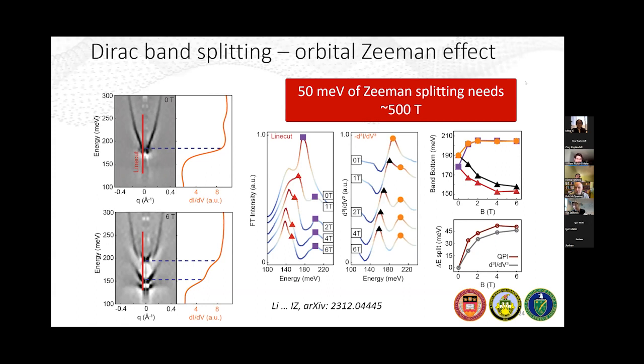What's really prominent in this system is this Dirac dispersion. Now we've imaged it in two different materials, and it seems like the 166 is not something you can see in other kagome systems. We studied a lot of these AV3Sb5 kagome superconductors, and we don't see the flat bands or the Dirac dispersion there in STM. You see other bands, but not this nice Dirac cone that you can see here. So this was very cool.